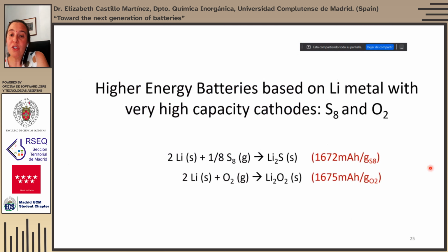So if we could use lithium metal with some of these polymeric, ceramic, or glassy electrolytes, what would be the best cathode material? Although we've seen many inorganic oxides, polyanionic compounds, phosphates and sulfides as electrodes, actually, in terms of capacity, we could even beat them with elemental sulfur and elemental oxygen. And that's what actually has been made. Their specific capacities for the formation of lithium sulfide and lithium peroxide are very large, more than 1,500 milliamp hour per gram. This is almost 10 times that of the largest capacity cathode material.